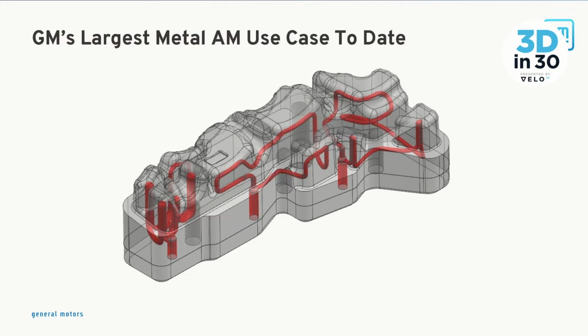Only without having to put in hundreds of individual spot coolers that are cooling individual areas, you can form very intricate circuits, simplify the plumbing on the tools, all while getting the water to where it needs to be. And what that means is when you look at a casting in general, there's always going to be areas that are thicker or some areas that are thinner, and you're just waiting to open that tool. If you can open it sooner, you're going to get more castings out of the process. Over a year, that's a significant amount of extra castings.